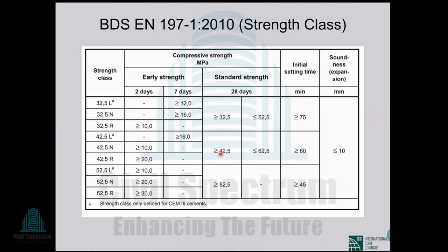For 28 days strength, there is an upper limit and a lower limit for the 42.5 strength class. The lower limit is that it must be greater than 42.5 megapascal, but there is also an upper limit. It must be less than 62.5 megapascal. In case of the 52.5 strength class, there is a lower limit, but there is no upper limit.